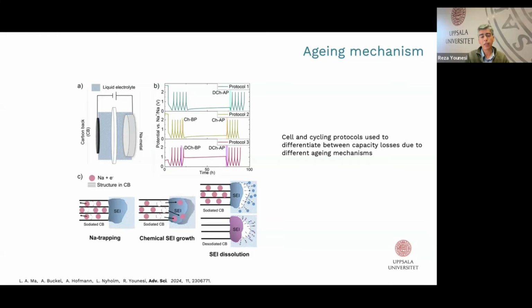The middle one is when sodium is lost because there is leak current at SEI. Basically, sodium ions can diffuse back from SEI while there is no external potential or current, and some of those sodiums are lost. On the right, you see the dissolution of SEI species at different states of charge, at sodiated or desodiated states.